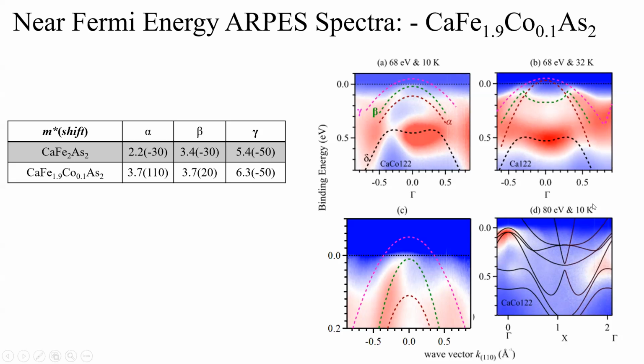So this part is basically the electron structure calculations using DFT. Since these band positions were not matching, I actually multiplied by some renormalization factor, and still I see that these band positions are not exactly the way I am expecting. So it means that these DFT calculations are not good enough to capture the things that we measure in the